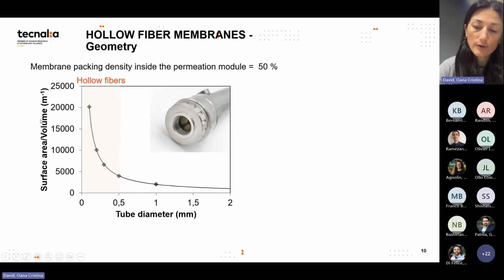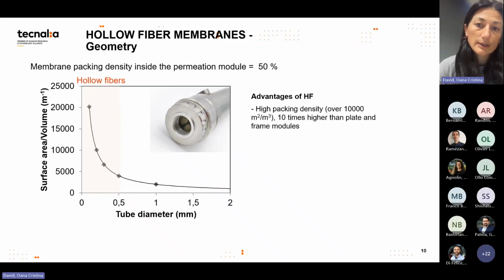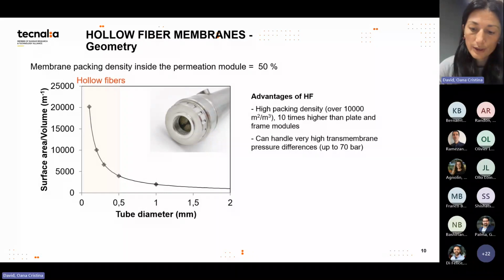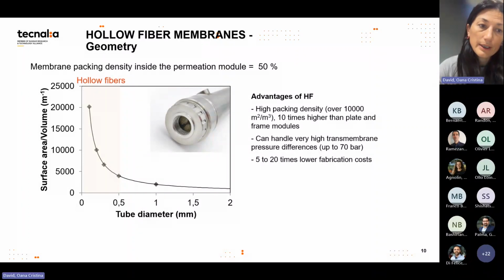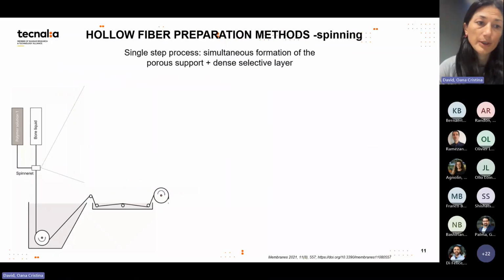So this is the advantage of hollow fiber membranes. It's 10 times higher than plate and frame modules, and the advantages of plate and frame modules were shown before by Heron. But also these small capillaries can handle normally high transmembrane pressure differences, up to 70 bars. And because both layers are made at the same time, because of this monolithic structure, we know that the fabrication costs are lower. So we only have one process to make monolithic hollow fiber membranes, and this is the spinning process.